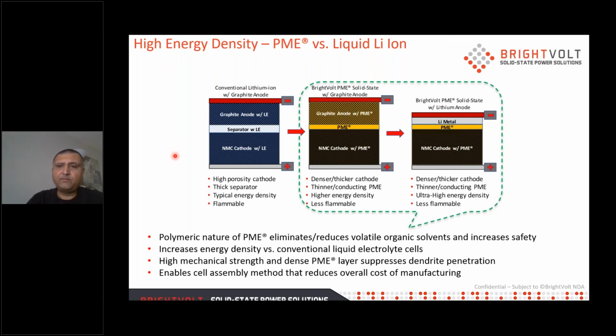Another benefit, of course, is that in a conventional liquid-based lithium-ion battery, the open pores are for that exact reason where you want to put the liquid electrolyte and create those conductive paths. With our technology, we don't have a need for that high level of porosity or low density, because we don't need to fill any liquid electrolyte since the PME solution is already in the slurry to begin with. And so that allows us to truly densify our electrodes, which results in a good bump in energy density. And also the fact that you're opening up a lot of volume in the cell by eliminating that liquid electrolyte. Also, if you were to cross-section one of the battery electrodes and look at the so-called PME-only layer that sits on top, it's an extremely thin layer that basically serves the function of a separator, and it's already in the sub 10 micron range.